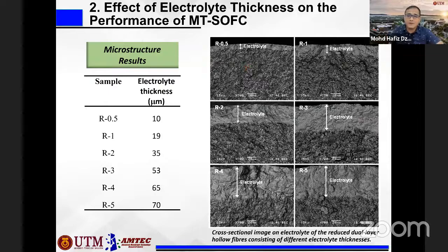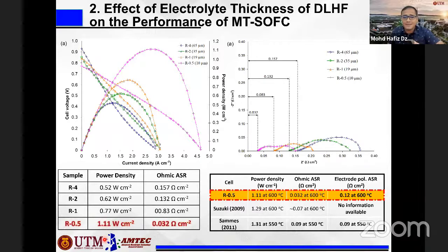By further reducing the electrolyte, we can increase the power density to 1.11 watt per centimeter square. This is because when we have a thinner electrolyte, the oxygen ions that transfer from the cathode to the anode have a shorter distance to travel. So we can produce a lot more oxygen ions in the anode, which react with the fuel and therefore produce more electrons. When more electrons are produced, more power can be generated.